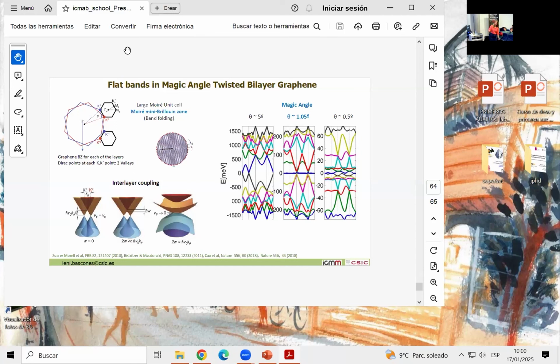Then you start hybridizing them. The two layers do not hybridize in the same way in all the Brillouin zone. Normally, the main hybridization is associated with the center of the unit cell or the vertices, because it's where you have atom over atom. And then there is a complex destructive interference process. That is, for twisted bilayer graphene, what gives the flat bands.